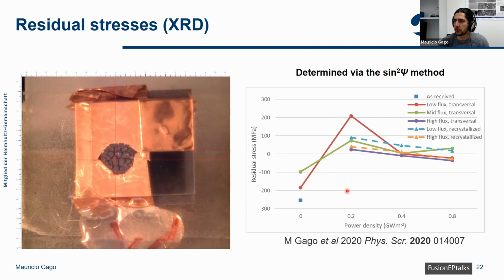But once power loads are applied, these compressive stresses at first turn into tensile stresses, which promote the formation of cracks. And after the power load is increased, so when the sample surface reaches higher temperatures, especially temperatures higher than the recrystallization temperature, then all stresses are more or less relaxed. So we then don't see a big difference.